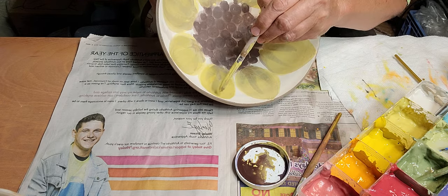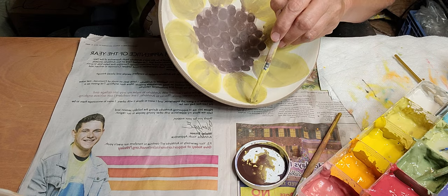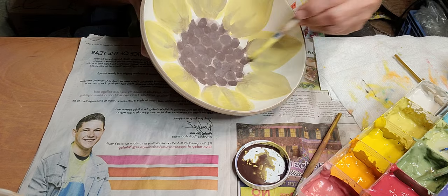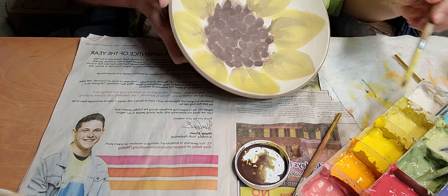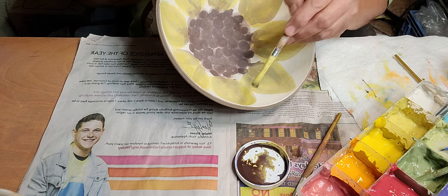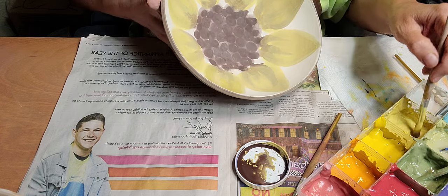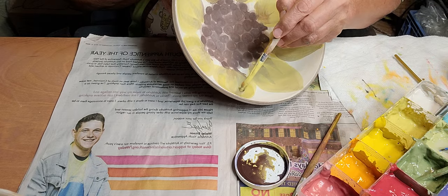You've got to be careful that you don't have any really thick spots, because they will pop through the clear glaze. It's like they suck up the flux that's in the clear glaze and you end up with a matte spot, which is not as food safe.